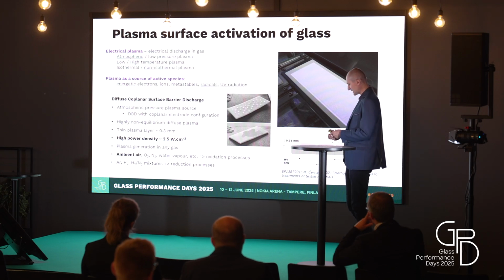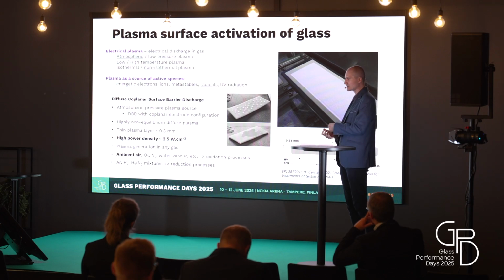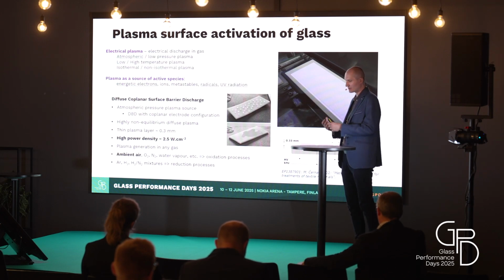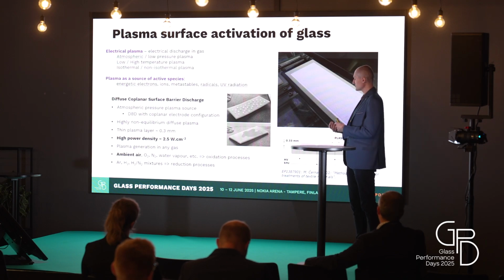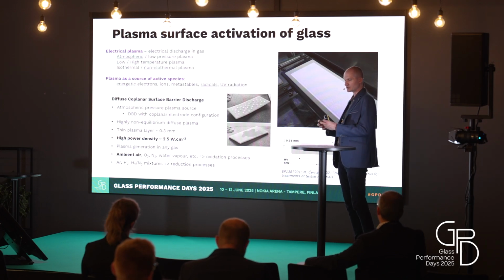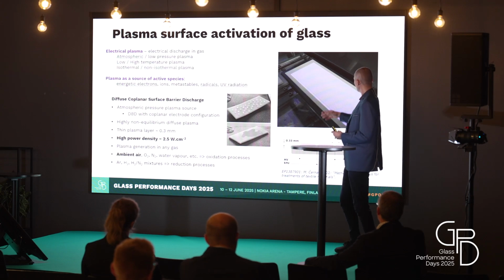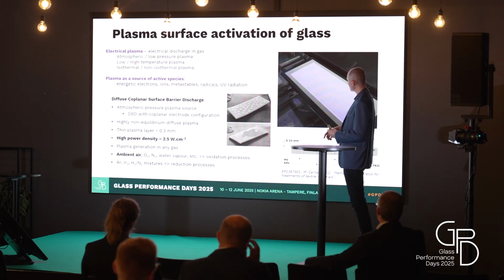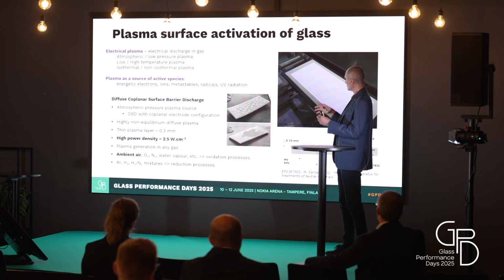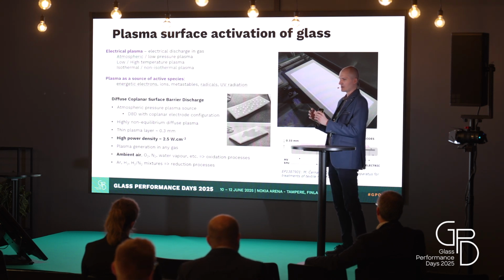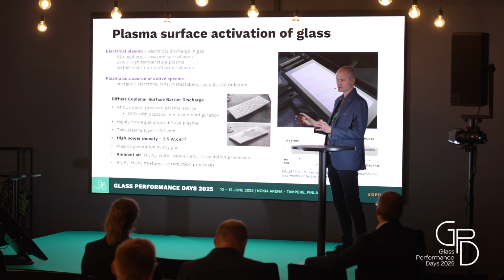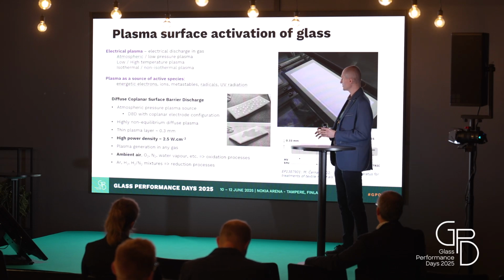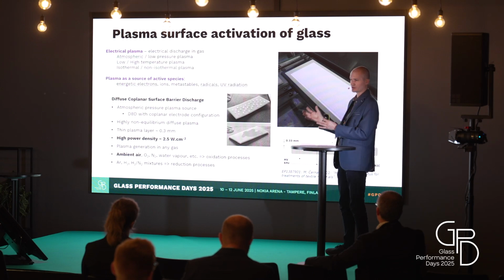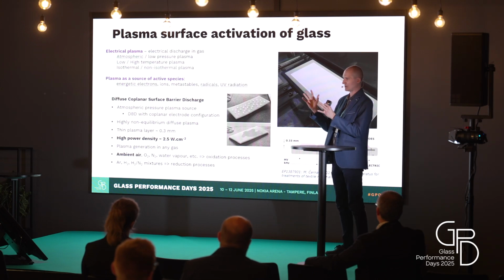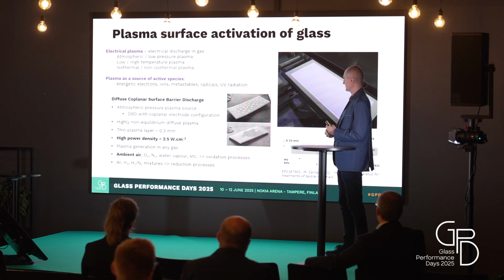Our plasma system looks like this. It would be very time consuming to explain how this works. Basically, you can imagine this is a system with which you can generate a thin layer of plasma on an area of roughly 8 to 20 centimeters. And you can generate this plasma in ambient conditions without any special gas. Of course, if you require some special application, you can work with oxygen or with some special gases, but you can generate plasma also in laboratory air. You can do it at atmospheric pressure.